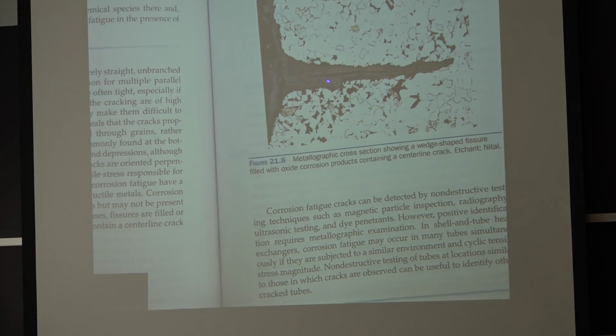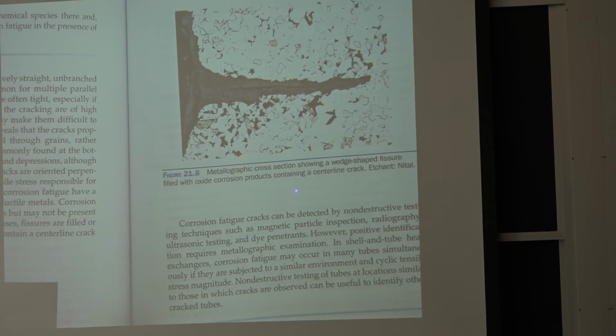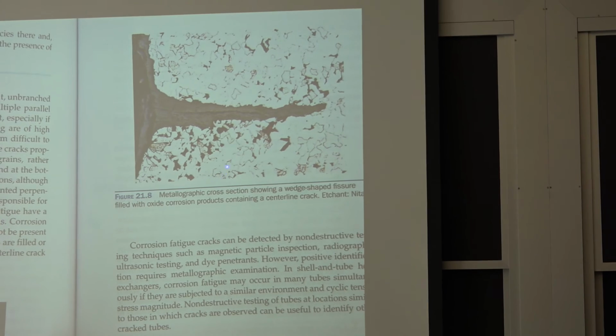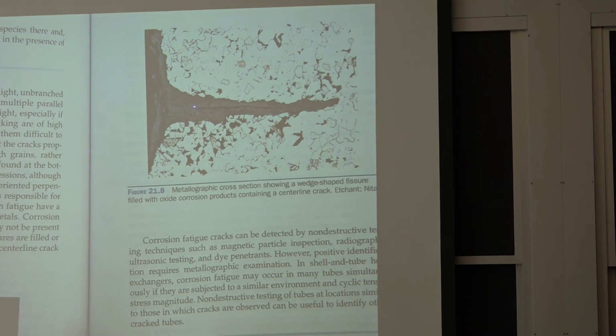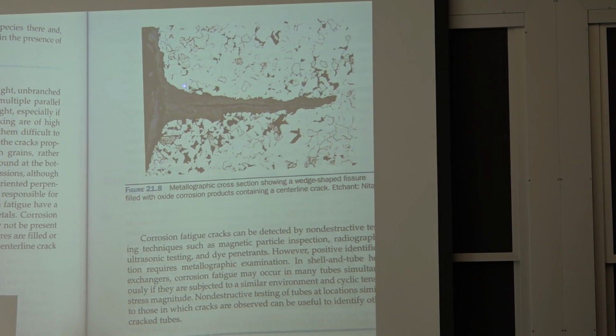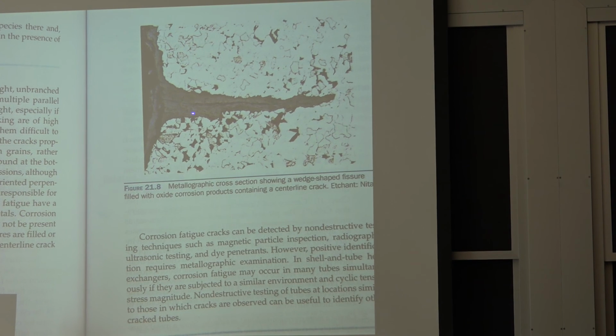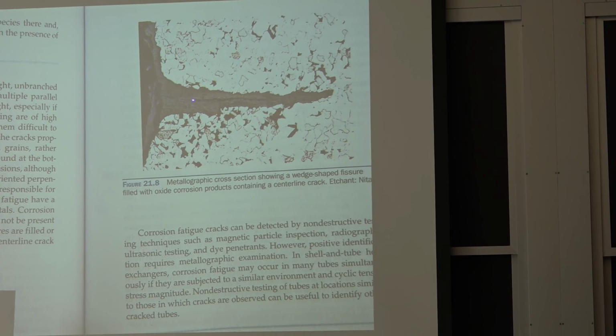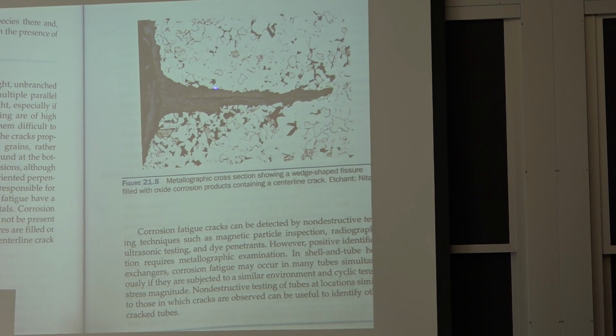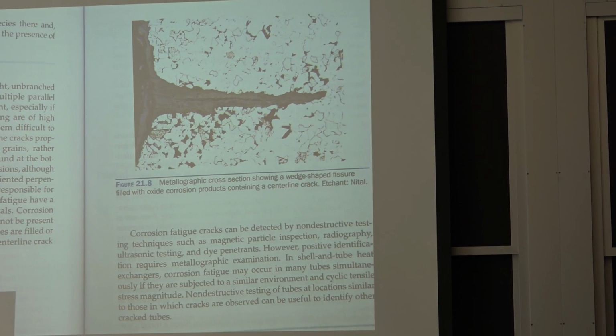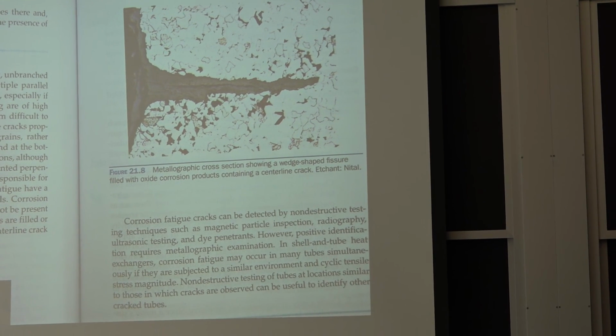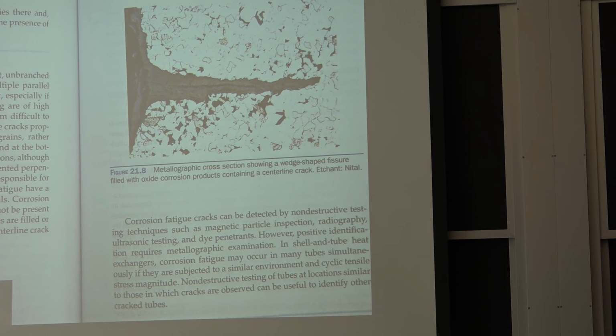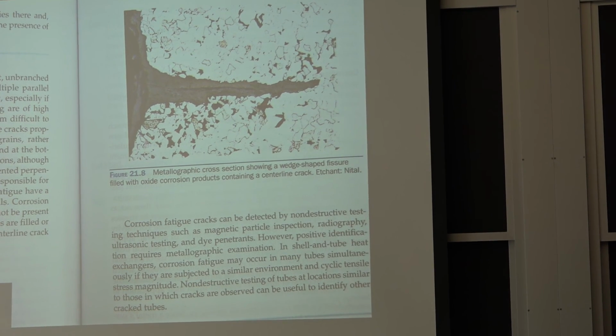This is a wedge-shaped fissure due to corrosion fatigue. Basically, the crack opens up on the first stress cycle. It starts to oxidize on the next stress cycle, but as the crack grows, you get a wedge shape. So whether it's thermal fatigue or corrosion fatigue, you see these little wedge-shaped cracks full of oxide, and that tells you the mechanism.